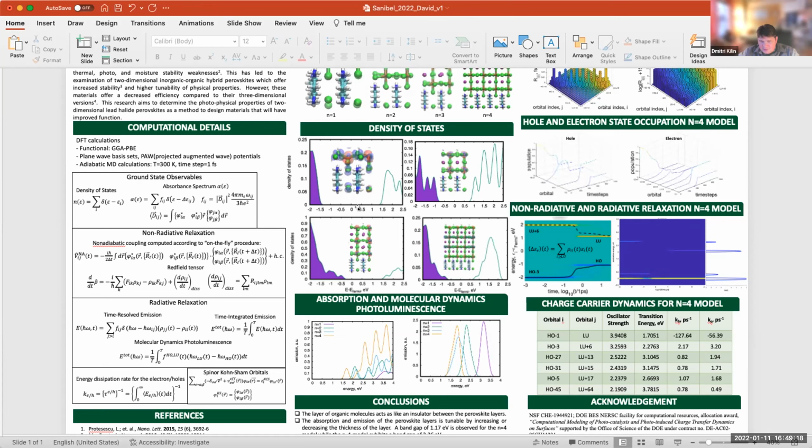And the third factor is that if one is doing an experiment, or trying to simulate the experiment, for a material at ambient temperature, not absolute zero, then there is inhomogeneous broadening. All interatomic bonds experience motion, and as they get closer or further away from each other, potential energy surfaces come closer or further from each other.